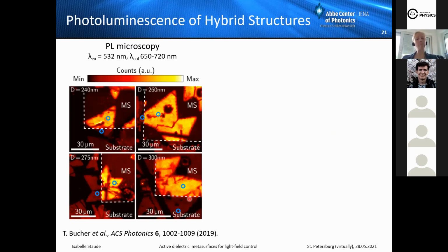So we were quite happy, but we also found that the photonic influence, whether this was really hitting a resonance or not, on the emission in the metasurface was quite negligible. There were mainly other factors, like the freestanding nature of the monolayer on top of the nanodiscs, which contributed mostly to this enhanced emission as compared to the substrate.